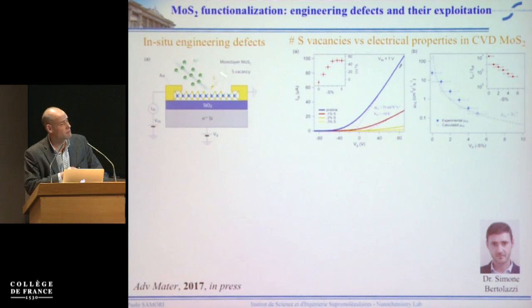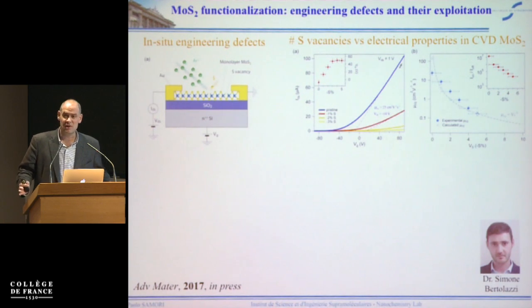So the approach is very simple. You use an argon beam, okay? With the argon beam, you increase quite drastically the number of defects, and this is what is reflected in the electrical characteristics. You can see that starting from the pristine, you can increase the amount of sulfur vacancies that are missing. So this is 1% of sulfurs missing. You can go up to essentially 35%, and then you don't measure any more current. But you can, if you want, continue your irradiation. You can essentially create a pure molybdenum type of surface.